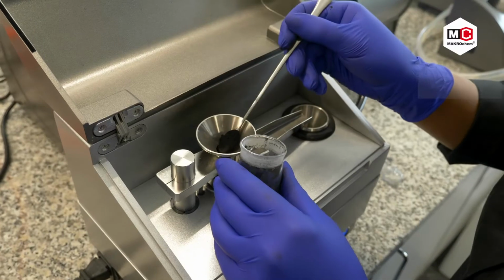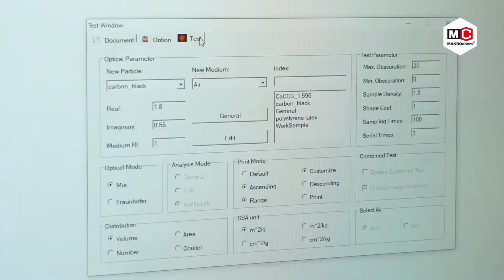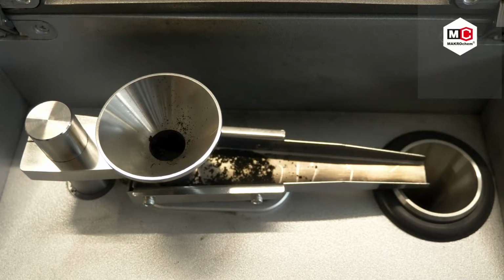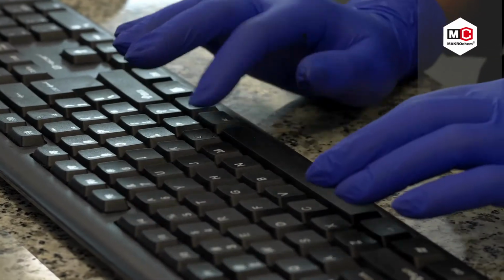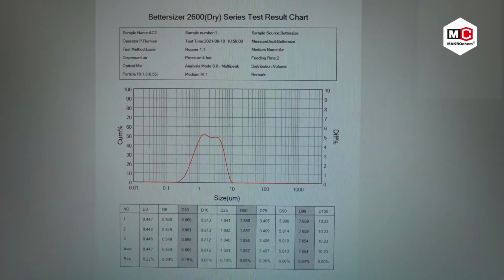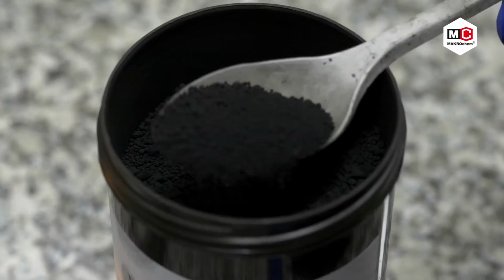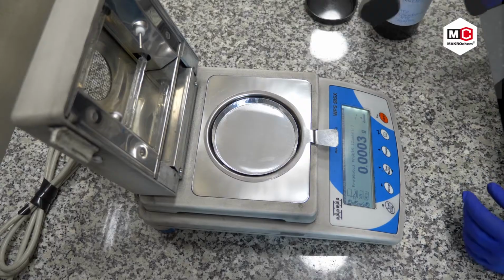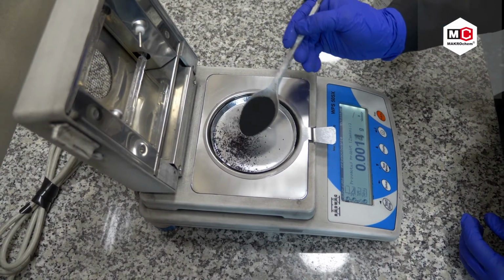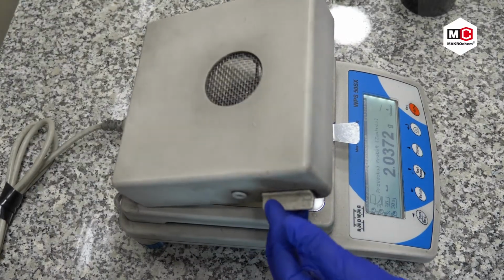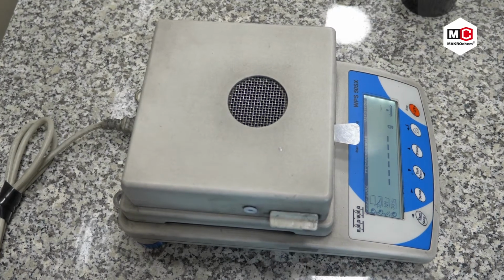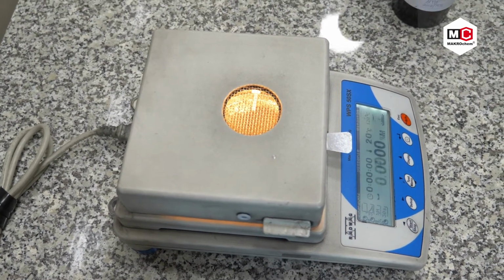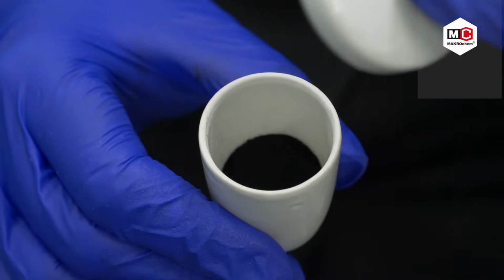Particle size distribution is an important parameter, especially in case of recovered carbon black. The measurement is conducted according to a proprietary method of the R&D Center, and the result describes dispersion capability in rubber compound. Subsequently, we evaluate the level of impurities in carbon black. First and foremost, moisture content. This is an important parameter. If the value is too high, proper rubber compound will be difficult to obtain and vulcanize.